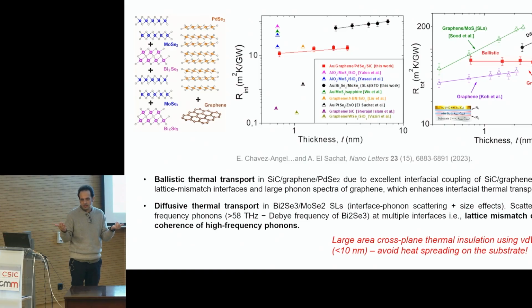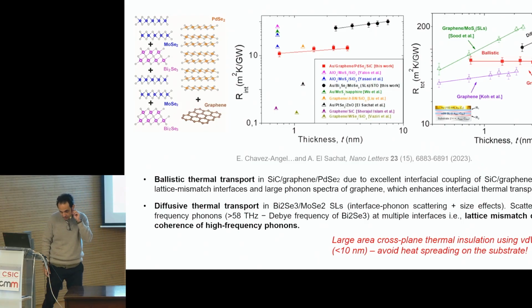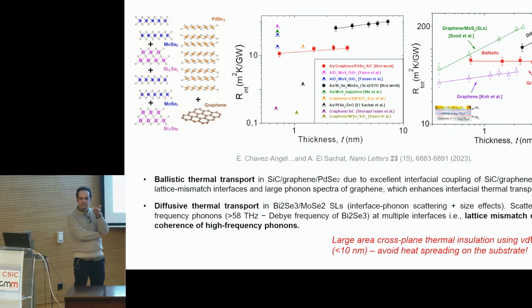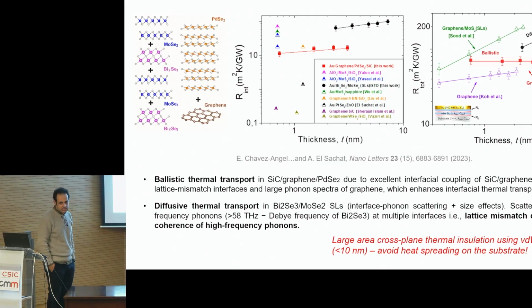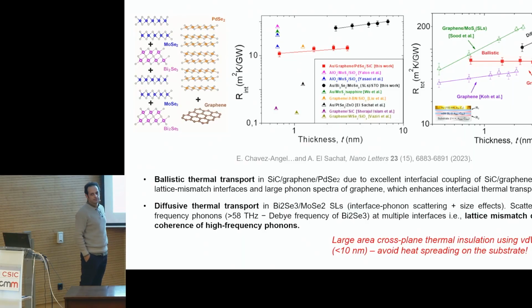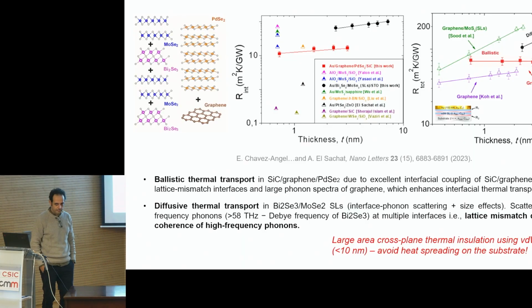Yeah, I mean, could it also be that you have a very large boundary resistance and what you're measuring is only that? No, but the thermal boundary resistance is exactly the first graph. Here it is 10 and the other is like 80. So the thermal boundary resistance is 8 times less than what I present in the second graph. So there is an effect of the boundary thermal resistance, but it's smaller. Okay, because it's a bit surprising, don't you agree? I mean, to see cross-plane ballistic transport.